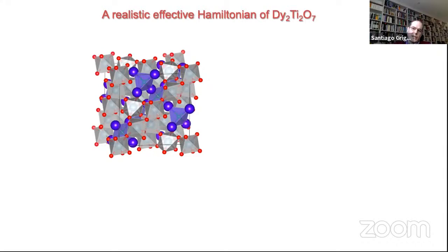So in some cases, I said, okay, well, we didn't take into account the dipolar interactions. And one thing I didn't mention, which maybe in a different format someone could have asked, is why didn't you do the experiment at lower temperatures? And that would be better, for example, for the Kasteleyn transition because you would be closer to the ideal limit. But the problem is that spin ice freezes at low temperatures. So if you go below 500 milli-K, the characteristic time becomes of the order of hundreds of seconds, and let's say at 100 milli-K, the characteristic time is of the order of a couple of months.